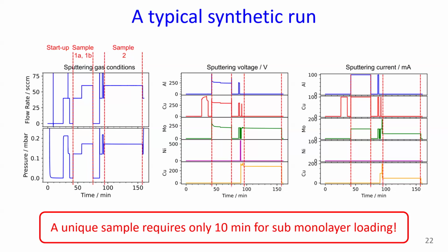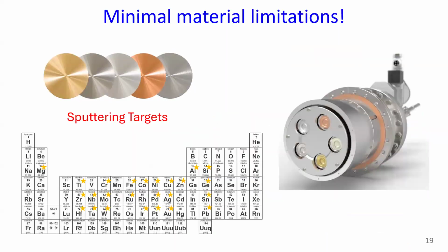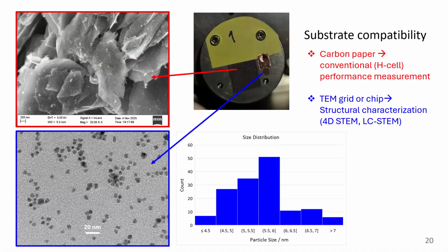Sorry, what's the monolayer coverage here? Yeah, for example, this would be less than a monolayer, because this is on stream. Whereas a lot of times, depending on what catalyst you're using, sometimes you need more. A lot of times particle interactions will affect the catalysis, and for some systems like our copper system, during the catalysis they'll fuse into nanograins, and so having those particle interactions can also affect the catalysis.